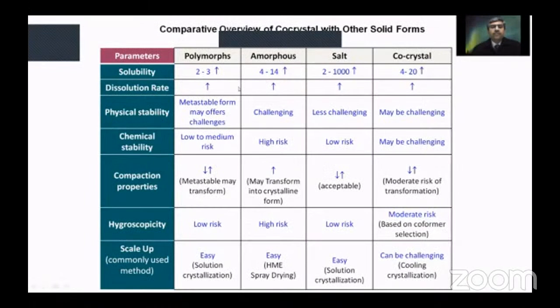In terms of the solubility advantage, they are comparable to the amorphous form, but additionally they have physical stability which is much better than the amorphous form, since the amorphous form is a high energy form and has a tendency to convert back to the crystalline form. All the solid forms, since they improve the solubility, will also enhance the dissolution rate. In terms of physical stability, co-crystal physical stability may be challenging, while the amorphous form is always challenging because it is a metastable form.